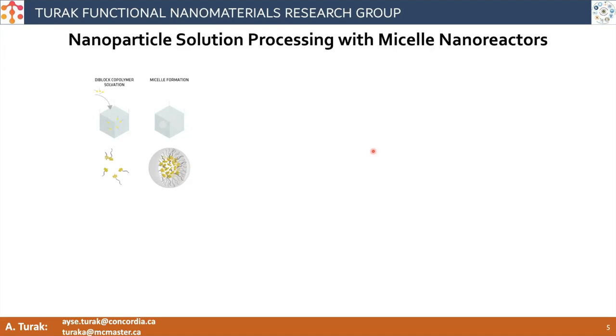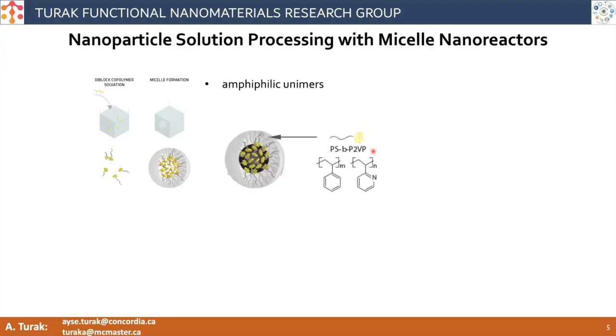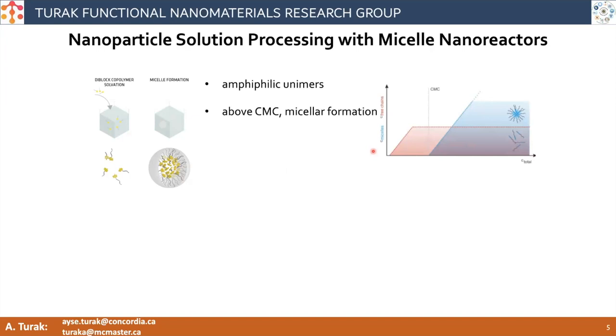What we do basically is take an amphiphilic unimer, right? Amphiphilic means that it has one hydrophobic and one hydrophilic end. So it's a polymer that has this dual nature. And typically we use polystyrene-b-poly-2-vinylpyridine, which is basically benzene-type rings attached to a long backbone. The polystyrene portion, where we have no nitrogen, is the hydrophobic part. And the 2-vinylpyridine, where we have nitrogen, is the hydrophilic part, which is the one that's more interested in water, while the polystyrene is less interested in water. When you take a diblock copolymer that has these two components and put it into some solvents above a critical concentration called the critical micelle concentration, these molecules will spontaneously combine into a macromolecule called the micelle.